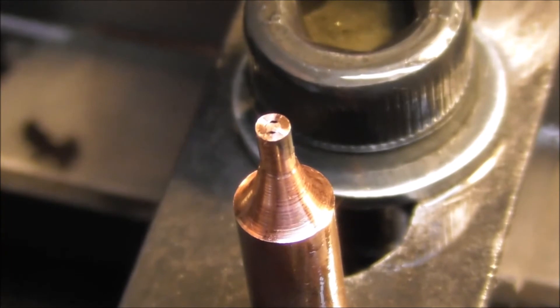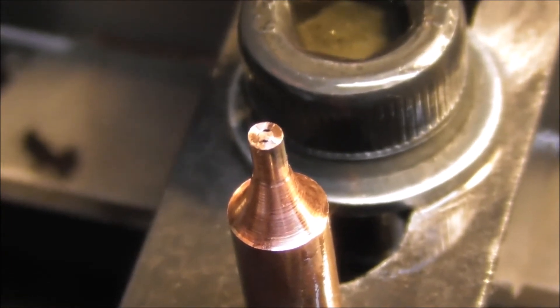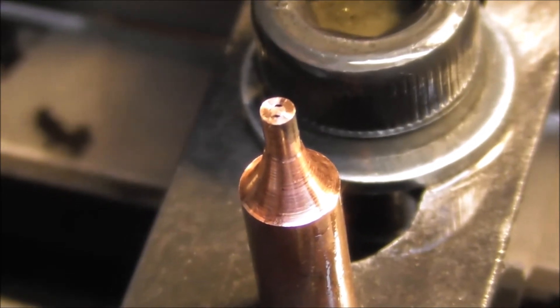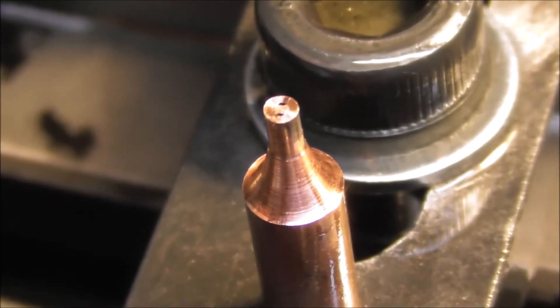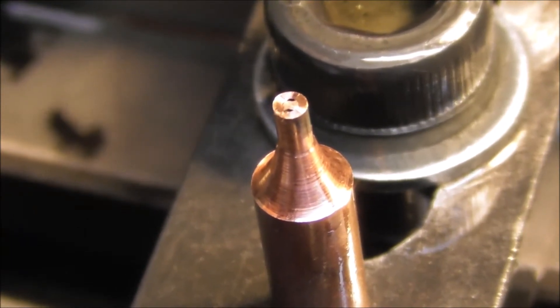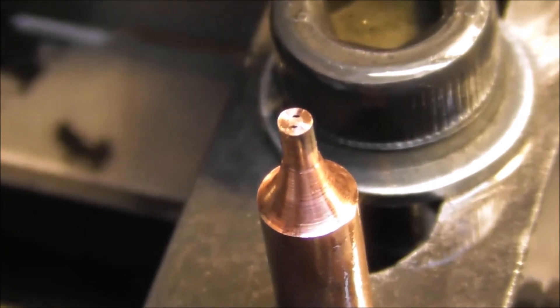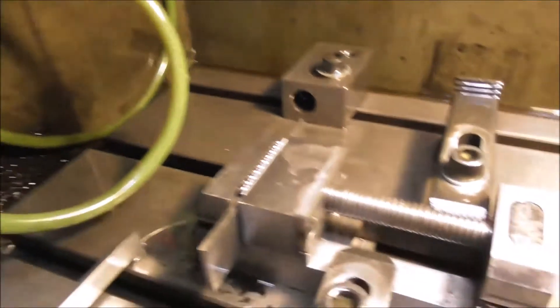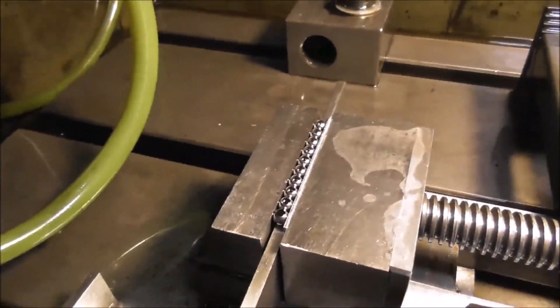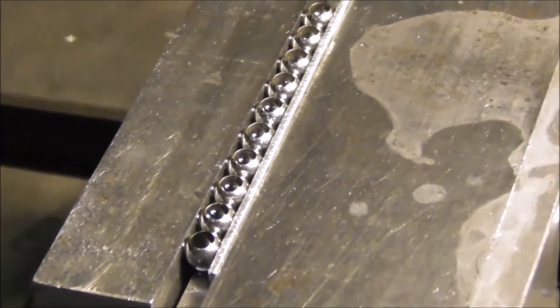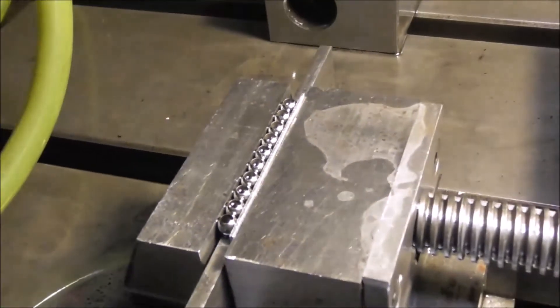You can just see it now, two tiny little holes and those holes are just big enough to suck the particles of eroded steel through but not big enough to cause other problems with spikes of metal going up inside it. And if the holes any bigger it's a problem and any smaller it's a problem and it has to be just the right amount of suction to suck the particles out and then it runs smoothly and automatically and I can go away and do something else. So it's all about automation.